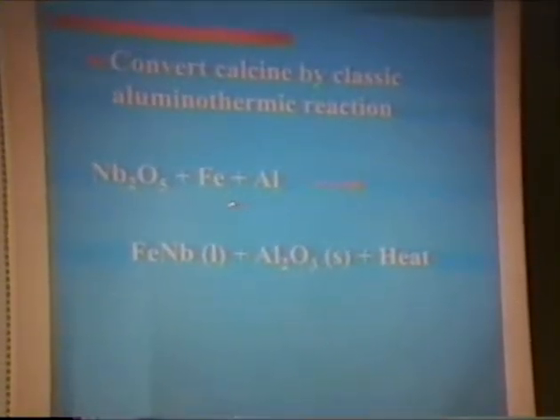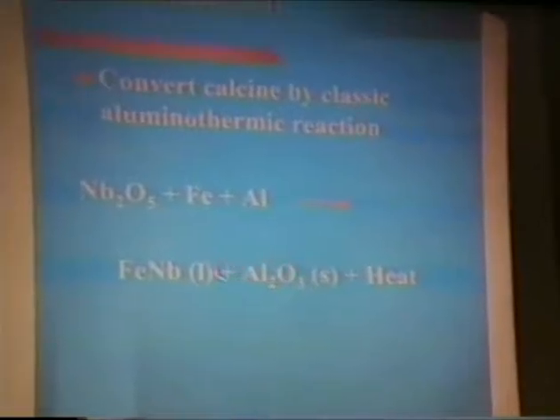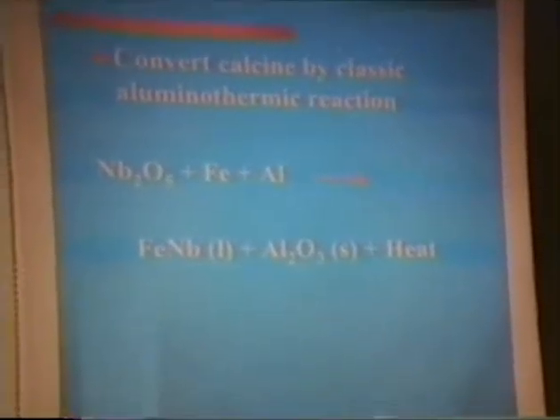Where basically you're transferring oxygens from niobium, in this case, to aluminum. This got so hot that you develop a liquid, a molten iron niobium alloy. Alumina is a light material that floats to the top of that, and you generate large quantities of heat. Once this material cools, you can then crack off the slag and further process.